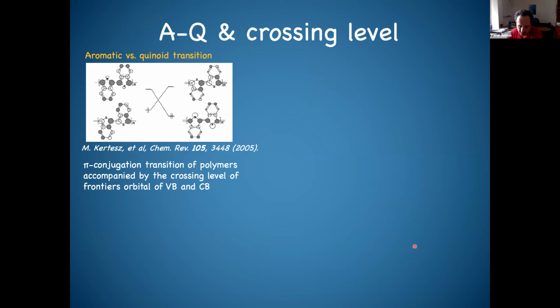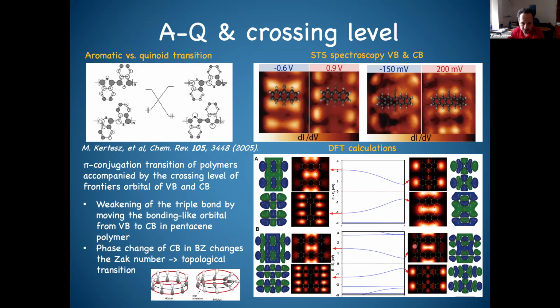And now I also mentioned, when we have this transition in the p-conjugation from aromatic to quinoid, this has to be related to some level crossing. So let's have a look at what we have in anthracene and pentacene. Again, I show you here these dI/dV maps of anthracene and pentacene. This is the valence, this is the conduction band of anthracene. And now you see that they swapped.